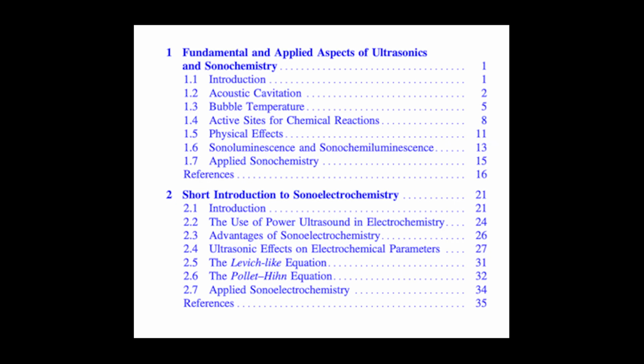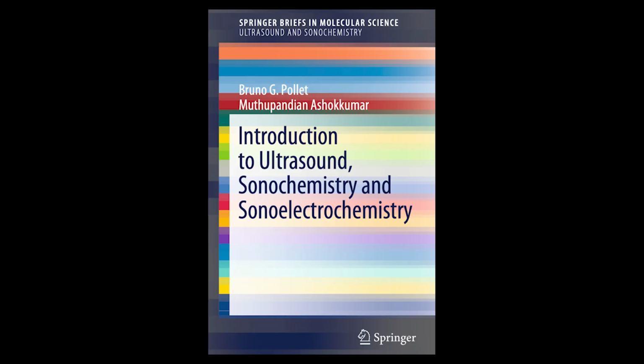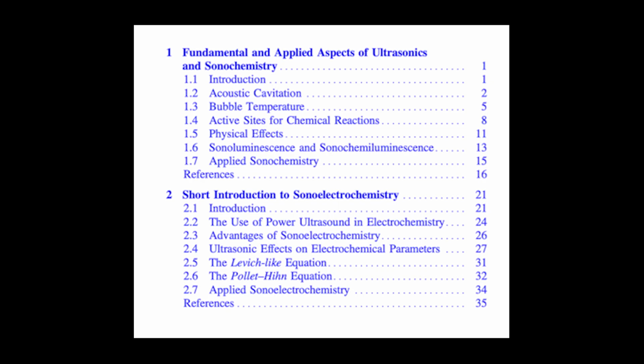Better rates, higher yields, less fouling, lower energy consumption. That's a pretty good list. Anything else? One more important one, particularly for electroplating and electrodeposition making coatings or materials. The physical agitation from ultrasound often leads to improved quality of the deposited material. You can get coatings that are harder, less porous, more uniform in thickness, and have better adhesion.